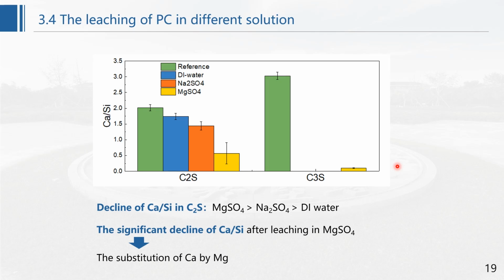Here is the change of calcium to silica ratio of C2S and C3S after leaching in different solutions. Among these three kinds of solution, the decline of calcium to silica ratio in magnesium sulfate solution is the highest. This should mainly be attributed to the substitution of calcium by magnesium during the leaching process.